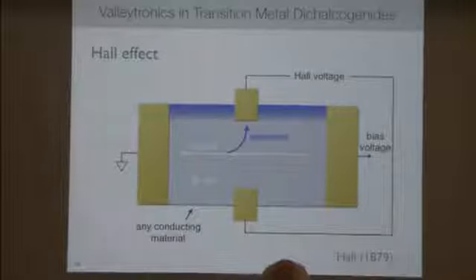So a first step in that direction would be to observe a valley-based analog of the Hall effect that's been known for a long time. And in fact, condensed matter physicists are frequently criticized for only ever measuring resistance as a function of magnetic field. And a big reason for that is our love of the Hall effect. The idea is just that when a current flows through a device in the presence of a perpendicular magnetic field, the electrons are deflected to one side of the sample, resulting in a voltage that can be measured. And it's one of the most important tools for characterizing semiconductors because, for example, depending on the sign of this voltage that you measure, you can find out whether the carriers in the material have positive or negative charge.